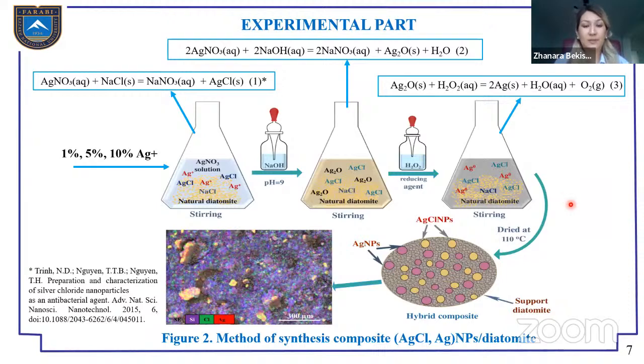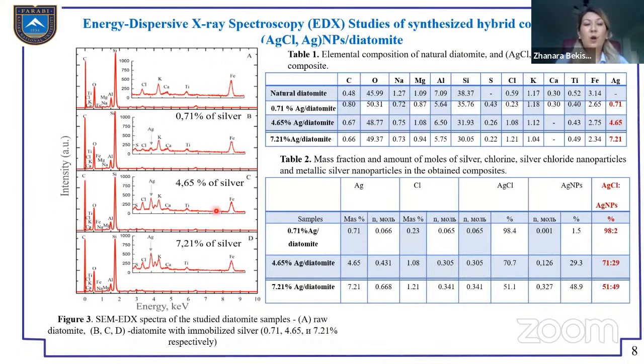And in the experimental part of synthesis of the hybrid composite, the diatomite mass was impregnated with silver nitrate solution with 3 initial concentrations: 1%, 5%, and 10% of the silver ions. First, it is an ion exchange reaction and formation of silver chloride. After that, the excess amount of the silver was basified with sodium hydroxide and reduced with the reducing agent hydrogen peroxide to form metallic silver nanoparticles. Then they were washed and dried, and we obtained hybrid composites with silver chloride and metallic silver nanoparticles on the diatomite support. With initial concentrations 1, 5, and 10%, the amount of absorbed silver equals 0.71, 4.65, and 7.21%. And the elemental composition is presented in table 1.